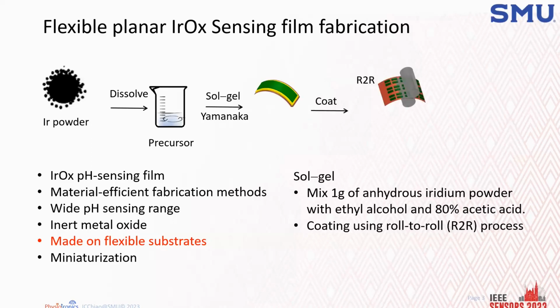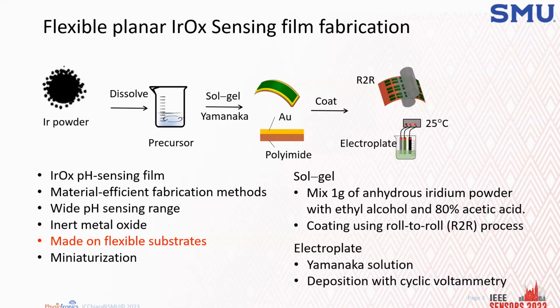One is that we prepare the iridium powder in a precursor solution and make a paint, and then we use a printing process, like printing a newspaper, on the flexible substrate. This is what we call the sol-gel process. After that, the printed substrate is baked in the oven to convert to iridium oxide. The other way is the traditional way: if there's a conductive metal on the flexible substrate, we can use an electroplating method at room temperature, and it will grow the iridium oxide directly on the film.